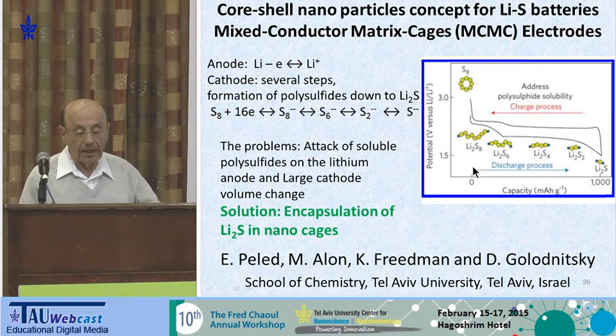So the idea how to solve these 2 problems. We had some thought to use what we call mixed conductor matrix cages, and to encapsulate the lithium sulfide, to start with the discharge state, encapsulate lithium sulfide into these cages, and when we charge it, the volume will decrease, and the polysulfide will not come into the solution.